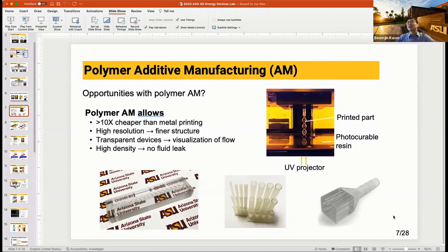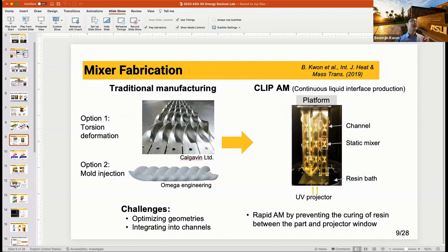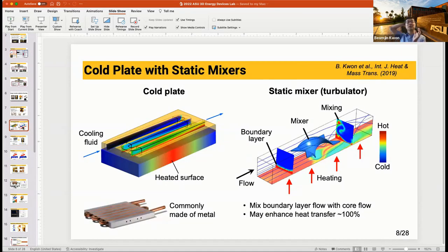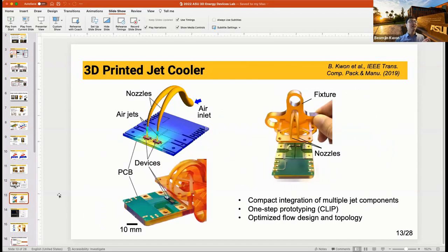And the material, of course, is very important for many applications. For many heat transfer systems, of course, we want thermally conductive material when you want to directly contact the hot spot. But in my research, I explored non-direct contact type heat transfer solutions. For the cold plate, the coolant directly contacts the hot surface, so the polymer doesn't directly contact it. And for the jet cooler, again, I'm only shooting the coolant onto the hot spot, so the polymer doesn't really directly contact the heated surface.